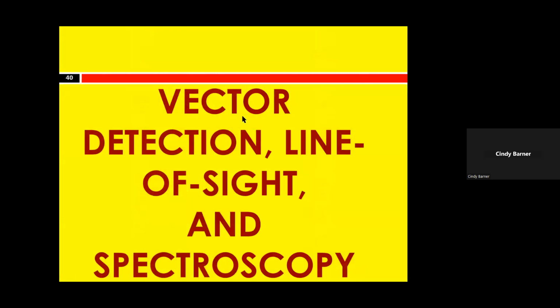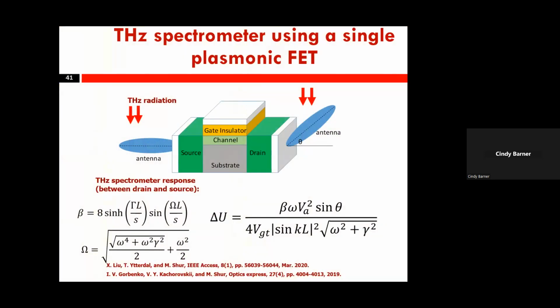And now I want to talk about vector detection, because I already mentioned in the beginning of the talk, when we go to 6G technology, it's very important to have both directed and broadband detection. And for line of sight detection, one way to do it is to detect not just the amplitude of the impinging signal, but also its phase. And here, the slide shows schematically how it could be done. If you have 2 antennas that received impinging terahertz radiation, but with different phase, then you could have the situation where by adjusting the density of electrons in the channel, you change the frequency of plasmonic oscillations, and therefore come to the situation where you have zero detection only at a certain frequency.